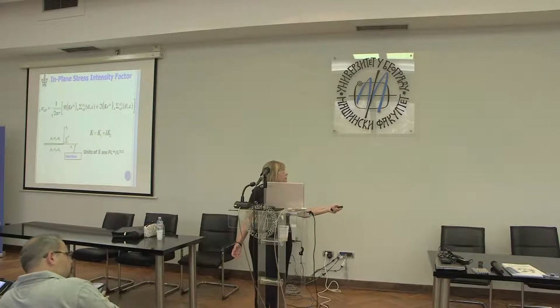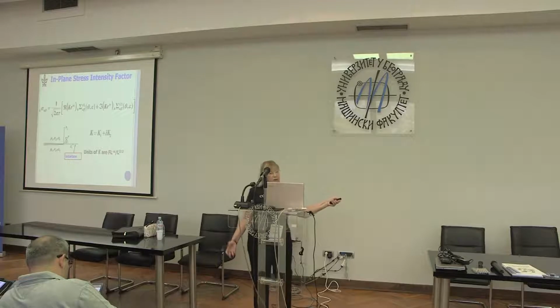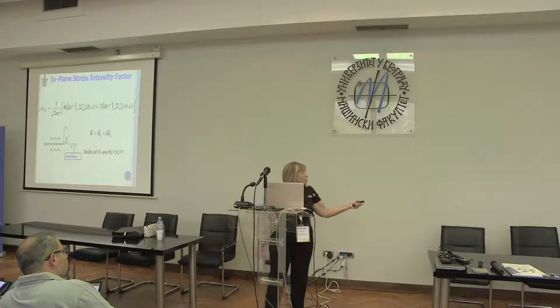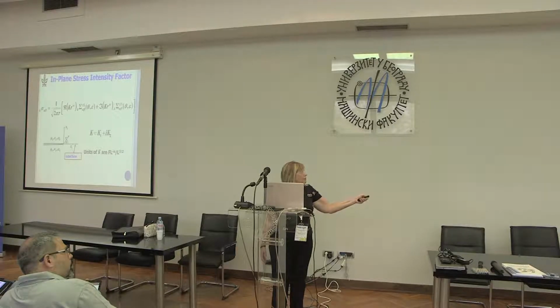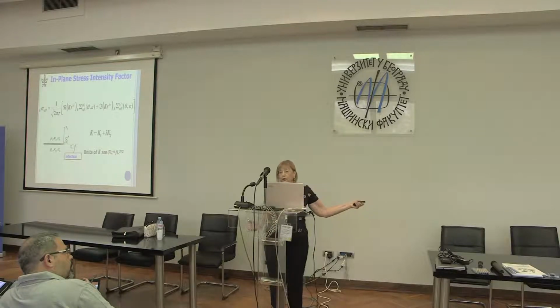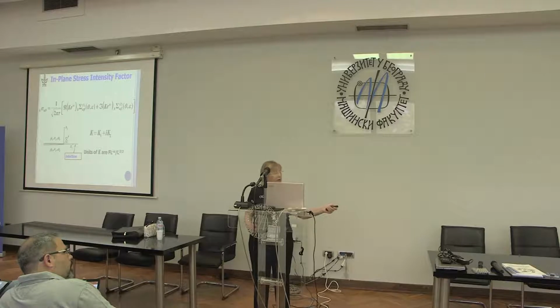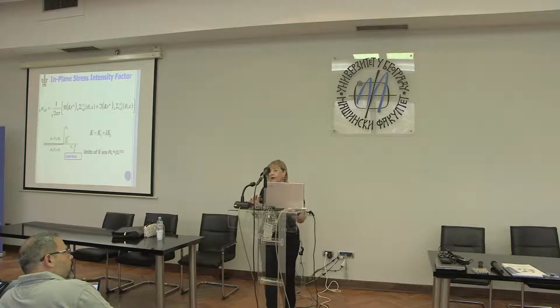Okay, so here's K, and what are the units of K? Stress has normal units. It's not complex, mind you. Sigma 1 and sigma 2 are real quantities, so sigma is just an ordinary stress, with units of force over length squared. If you go through this, you can see that K has units of force times length to the -3/2, which is what you usually expect for a stress intensity factor. But then we have this L to the -i epsilon, which is maybe a little bit uncomfortable, and we have to learn how to live with it.